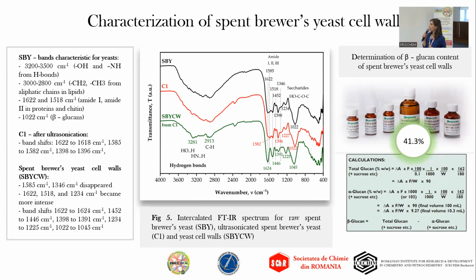The spectrum of the optimal sample presented some band shifts in comparison with the raw biomass. However, the most noticeable changes were observed when comparing the optimal sample to the spent brewer's yeast cells. There were some bands which disappeared, for example, the 1585 band and the 1346 band. Some bands became more intense, and there were also some band shifts. Overall, the spectra confirm that there are indeed spent brewer's yeast cell walls in the sediment that we collected after sample processing. That was the aim of the assay.